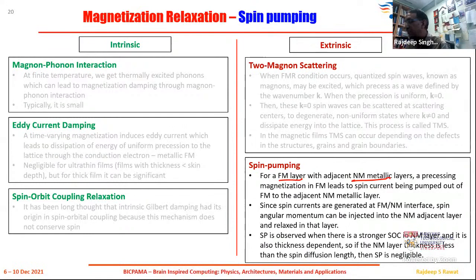Whenever you have a ferromagnetic layer together with an adjacent Pt layer, and you subject this ferromagnetic layer to an external oscillating RF field, that means HRF, then the magnetization will start to precess in this ferromagnetic layer, and this precessing magnetization pumps the spin to the adjacent non-magnetic layer. That is what is called spin pumping. That pumping takes place only if there is an adjacent layer. At this interface, there's a loss of angular momentum from the ferromagnetic layer, and that leads to the dissipation of the energy of the magnetization in the ferromagnet, and that leads to relaxation. So that is what is called relaxation due to spin pumping.